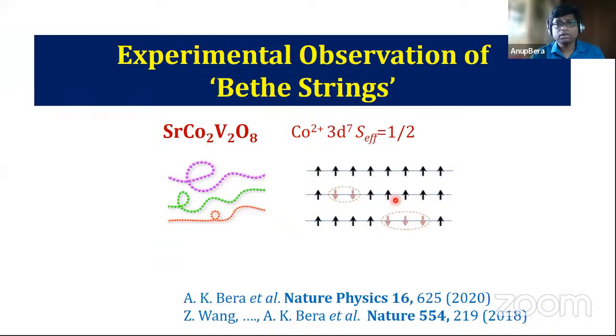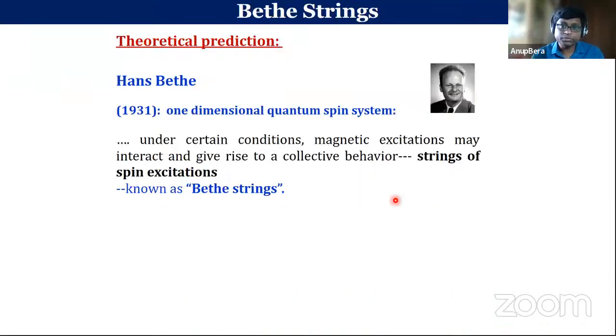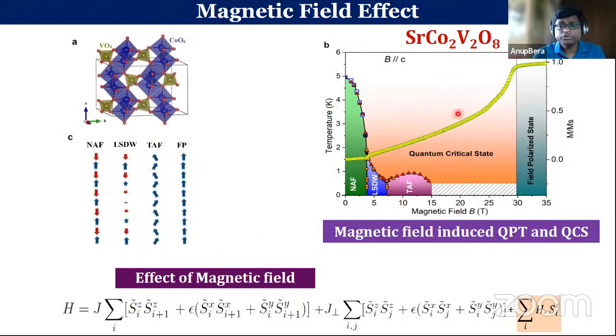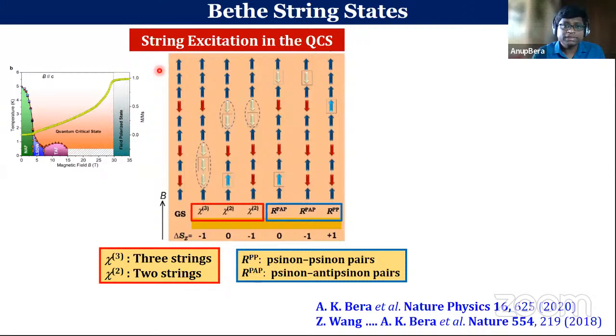Now I'm coming to the other quantum phenomenon that we have recently observed in this system, which is the Bethe string, first proposed initially by Professor Bethe. He says that in certain conditions, the spin excitations can interact with each other and form a kind of string. And if we switch on the magnetic field in this system, we can suppress this Néel order and go to a quantum critical state. In this quantum critical state, the spins are continuously fluctuating, but if at a certain time I take a snapshot, we see that this is the ground state.